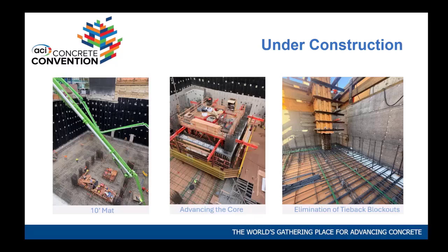You have trucks coming in. So think about it, 10 feet of concrete, it's mass concrete. There's a high heat of hydration, so we always make sure that the cement content of these mixes is less than 450 pounds, and we kind of extend the strengths, so you don't need that strength till about 90 days or 120 days to make it easy on the ready-mix guys to bring those mixes to us. If you pour that mix like a regular 6,000 mix with 600-pound cement, you won't be able to walk on it in 2 days. It's going to be very hot.